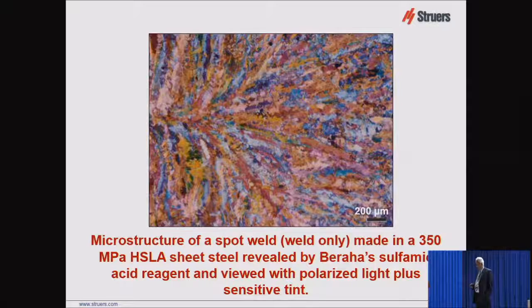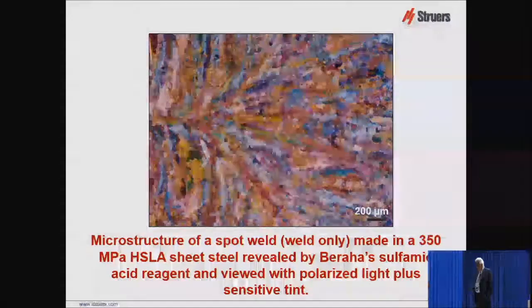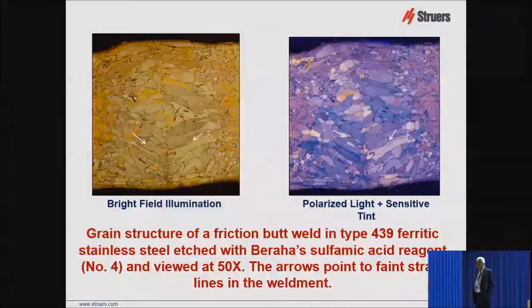Unfortunately, I don't have a black and white example of this same etch, same sample in the same area at 50x, to show you, but I can tell you that you can't see that structure anywhere near as well as you can here. This is only a 50x, but it's a beautiful pattern. And we're also viewing that in polarized light and sensitive tint.